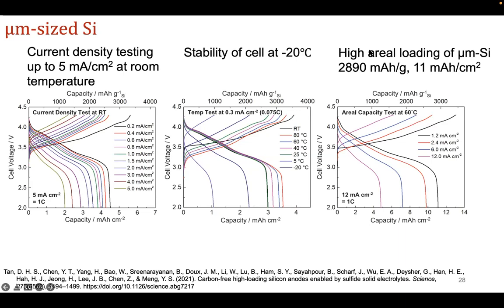Now, in terms of testing current density and rate capability, and also stability at lower temperatures and higher areal loading of micron-sized silicon, they performed all these tests, and these micron-sized silicon electrode composites perform pretty well. In the room temperature current density test, while there is a fade going to higher current density, it's still achieving thousands of milliamp hours per gram. At low temperatures it retains high performance at high C rates. And as you increase the mass loading of silicon, although this is at 60 degrees Celsius, it can also maintain high electrochemical performance.